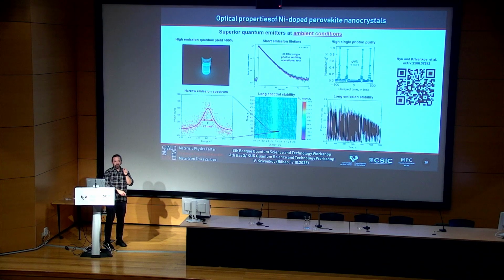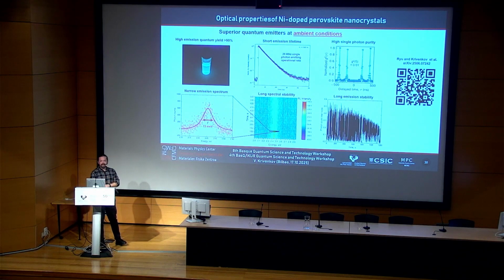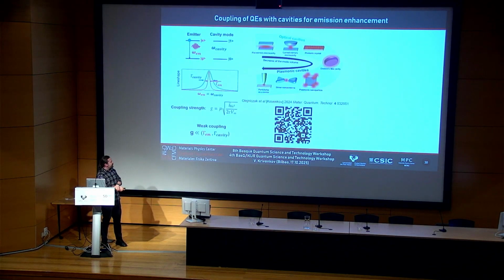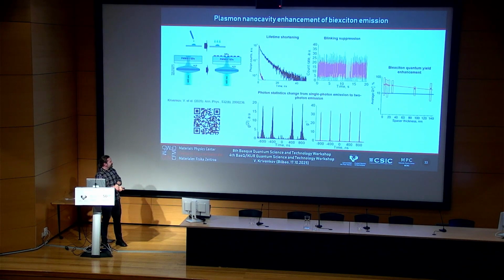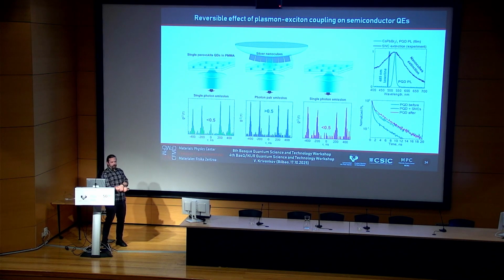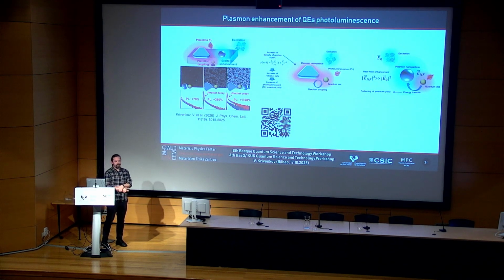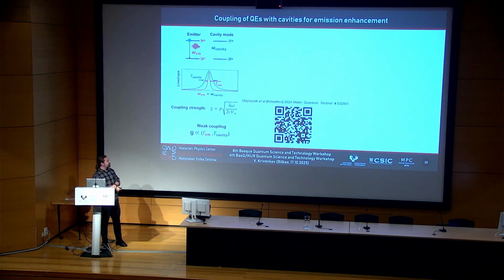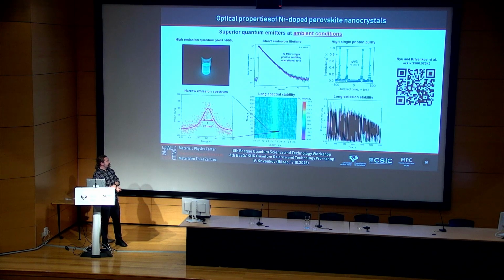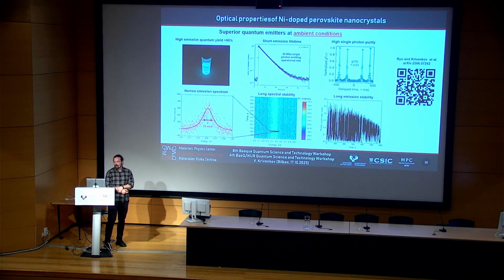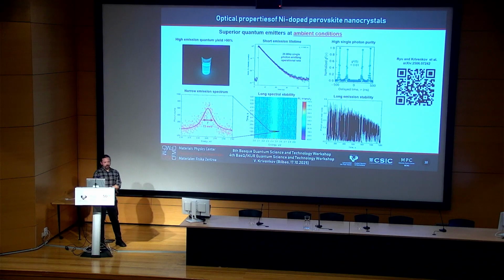Yes, then we are sure that we don't have a second photon, because actually in semiconductor quantum dots, there's not ideal single photon purity. It is related to the biexciton emission, as I showed you earlier. When we increase the biexciton emission, we are ruining the single photon purity. But if we eliminate the biexciton state altogether, as we performed in our perovskite nanocrystals, where the efficiency of the biexciton transition is almost zero, then we don't have the second photon coming from the quantum dot, and we always have only one photon. So it's an interplay, depending on what we want to achieve. Oh, thanks.